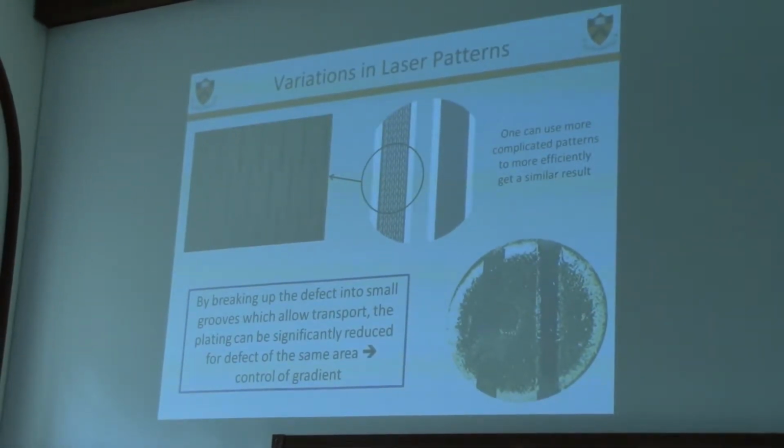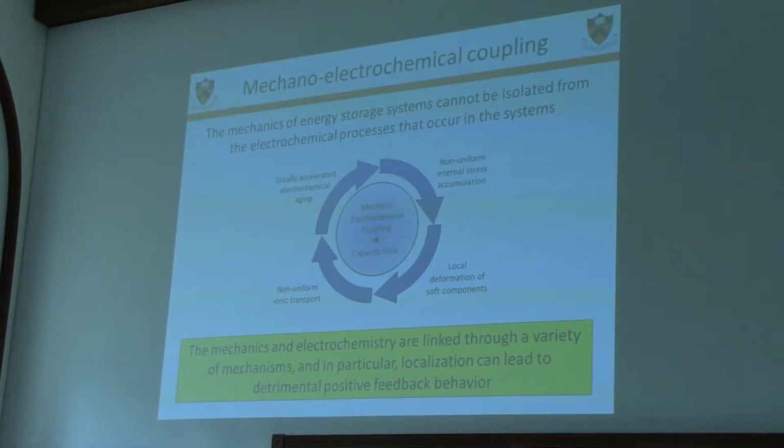One of the other fun ones is we can cut things up with a laser also, right? So here I've cut holes in this with a laser with some kind of crazy patterns here, and you can see again I can get rid of the formation of plating even though I have the same area. So let's kind of summarize the talk, okay?